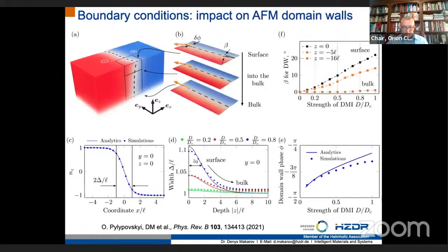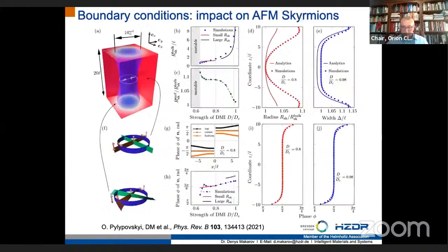A qualitatively similar picture can be obtained also for non-collinear textures, where an antiferromagnetic domain wall, for example, also gets modified upon approaching this edge of the sample. It gets broader, the plane of the domain wall also gets modified, it acquires a tilt and also a bend, and the direction of this bend is determined by the sign of the Dzyaloshinskii-Moriya interaction. A qualitatively similar picture is observed also for antiferromagnetic skyrmions.